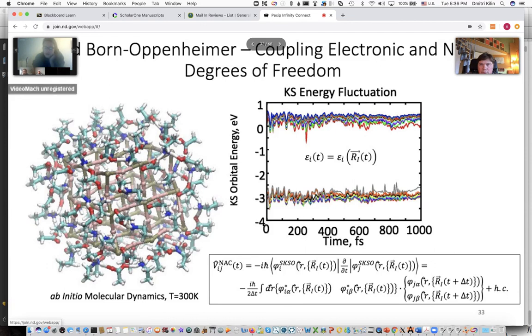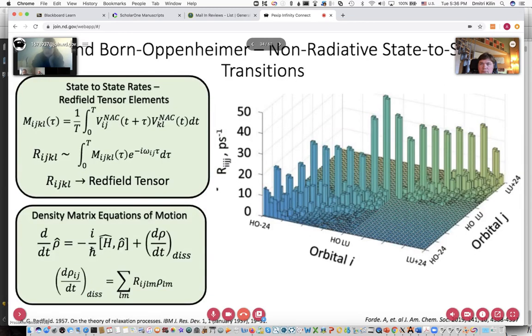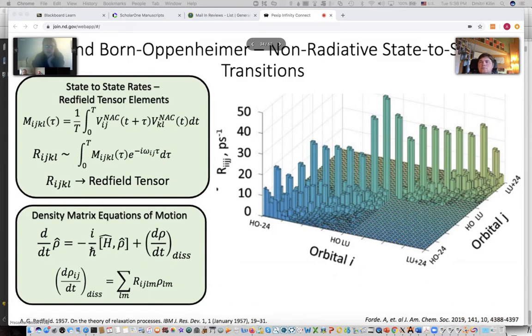And then we compute our non-adiabatic couplings along this trajectory, which is this bottom equation. And I know that we use the spinor orbitals. And so we compute our couplings. And to make them useful for our dynamic equations, we have to turn these couplings into rates or frequencies. And to do that, we take correlation functions. So this first equation between non-adiabatic couplings in the time domain, which is this M_IJKL. And then to get frequencies, we take a Fourier transform, which gives us this big R_IJKL.